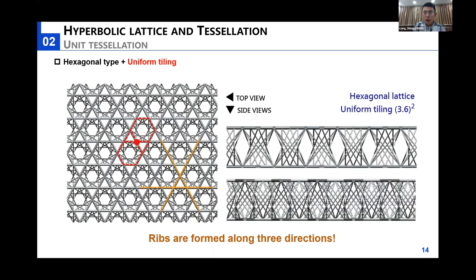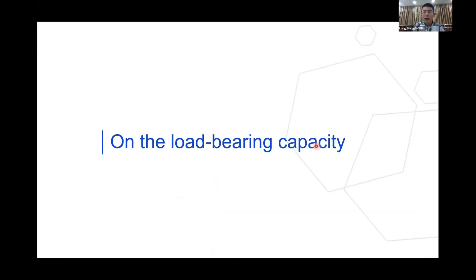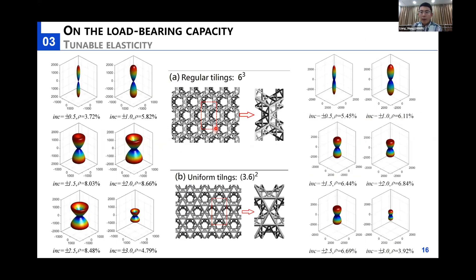For both of these structures, after their tessellations, the mechanical properties are studied and their load-bearing capacity is compared. We have employed the asymptotic homogenization approach. Here is a spatial distribution of Young's modulus with varying inclination angles of lateral struts. We observe that all the surfaces take an hourglass-like feature, implying that the materials are transversely isotropic.